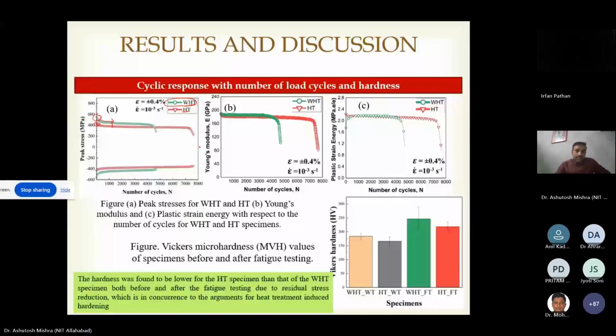This graph also tells us that peak stress is reducing with number of cycles. The other thing is we have compared Young's modulus also. Young's modulus is slightly more for WHT, instead of what we were expecting, that we'd get Young's modulus more for HT. This is the case where we are actually focusing our further studies. So why do we have Young's modulus greater for without heat treated and lesser for heat treated, although fatigue life is more? The reason which we have obtained so far is that microstructural coarsening can be the possible reason. However, it requires further substantiation. So my group is carrying out certain other tests which require further validation of these particular results.